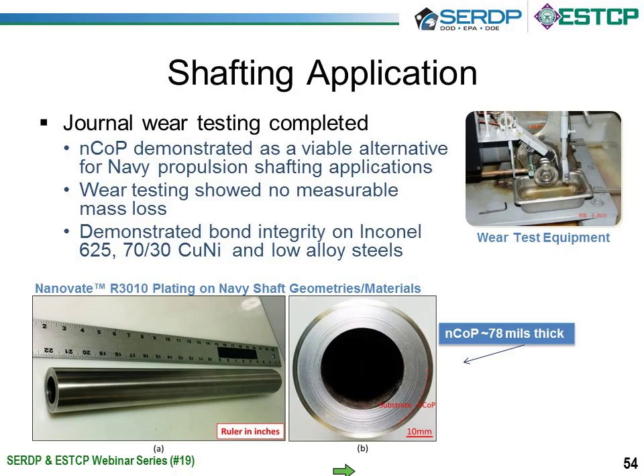And finally, as a secondary offshoot, we explored the ability to do large thickness deposits. This was a request from our NAVC participants to evaluate the ability to repair propulsion shafting on the ship side of the Navy. This wear test evaluated the R3010, or in this case, in this slide, the NCOP coating. You'll notice here that we were able to obtain 78 thousandths thickness, which is illustrated right here, where you can visually see the coating deposit. Quite interesting, number one, that we can go that thick, and we can also do it quite quickly. And that's what led us to think about other usages of this technology that we'll show in future work.